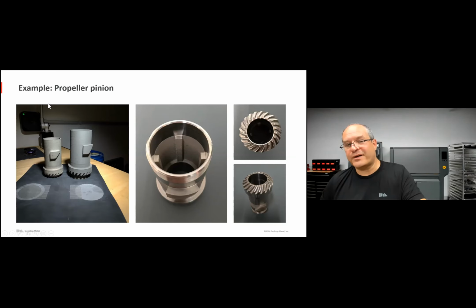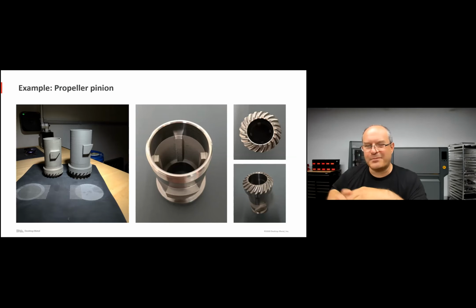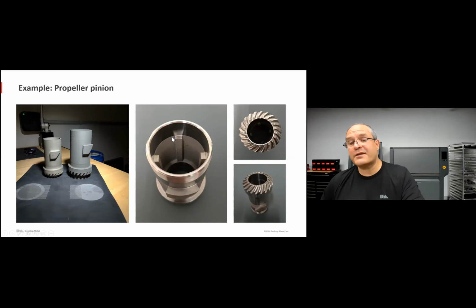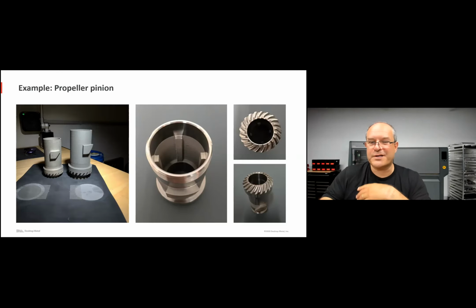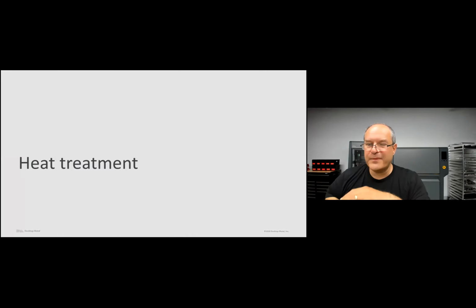With 3D printing, you print the part, sinter. So what you're seeing here is the shrinkage in the furnace. Don't worry, the software takes into account the shrink by scaling the part up appropriately. And then the blank is machined. What's great here is by printing the part much closer to the final shape, there's actually less machining required. And you see these are the machined surfaces, and the part works great. And so now, instead of casting and waiting for the whole casting operation, alloy procurement, wax setup, tooling, you can just simply 3D print on demand what you need.